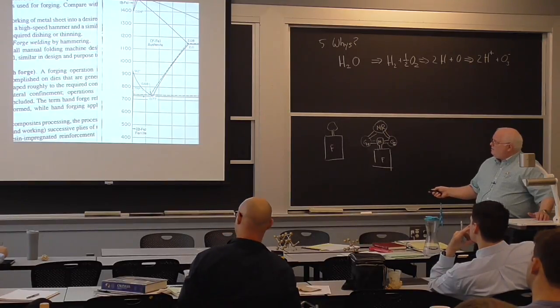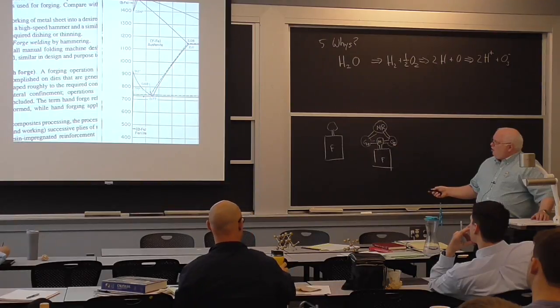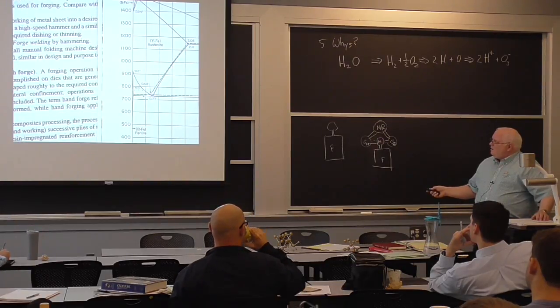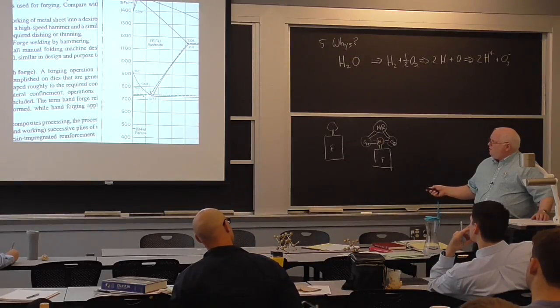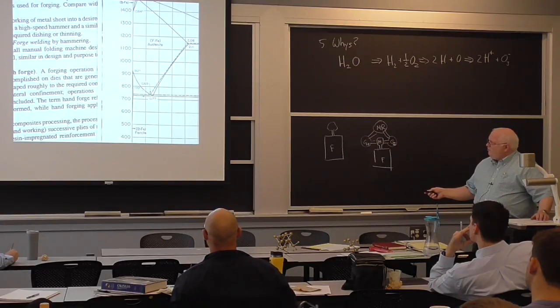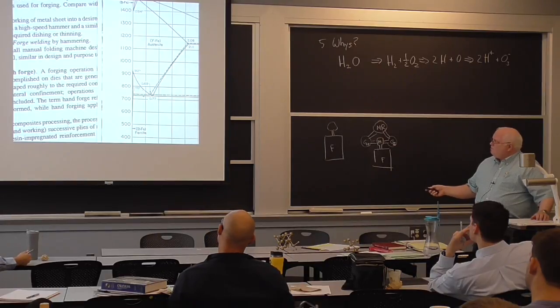Here at 0.77, carbon is the lowest temperature at which austenite is stable. This is a solvus line for carbon in austenite. This is a solvus line over here for carbon in ferrite. In this region, you have both of them, and you have to heat up above this line.